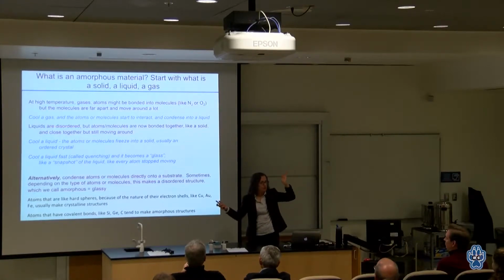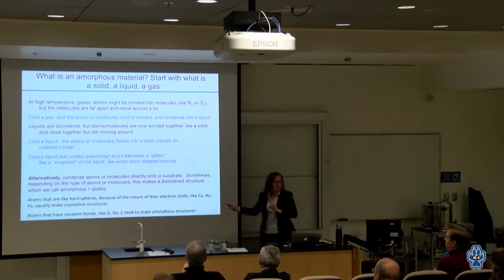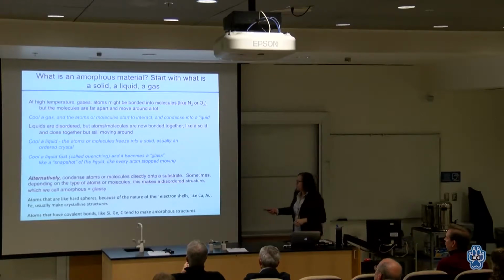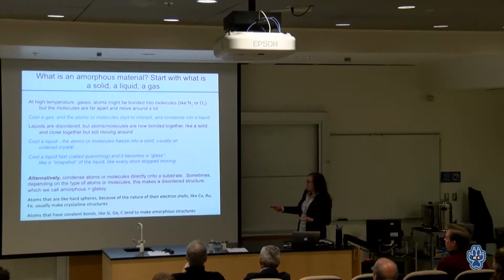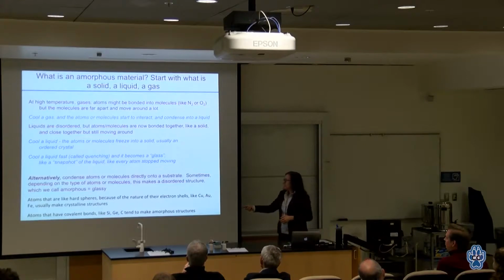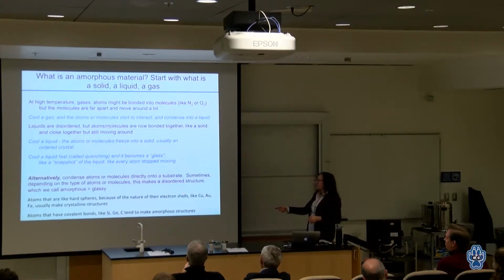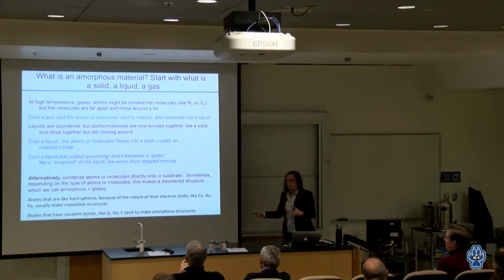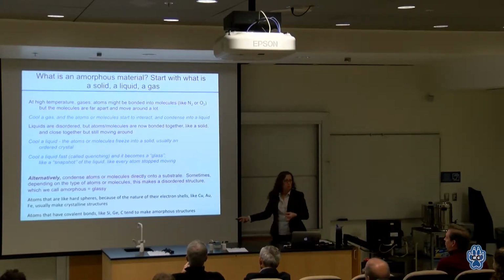They're very far apart, so it really isn't vapor quenching, but it is a terminology that's often used. It depends on the type of atoms or molecules what happens. Sometimes it makes a disordered structure, which is traditionally called amorphous, but is really equal to glassy. If there are hard spheres, because of the nature of their shells, like copper or gold or iron, they usually make crystalline structures. But atoms that have very strong covalent bonds, like silicon and germanium, with these P bonds that stick out, tend to make these amorphous structures.